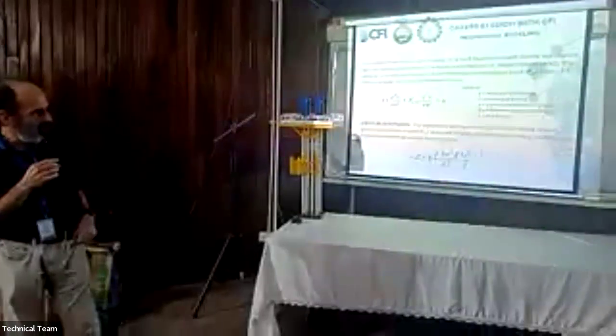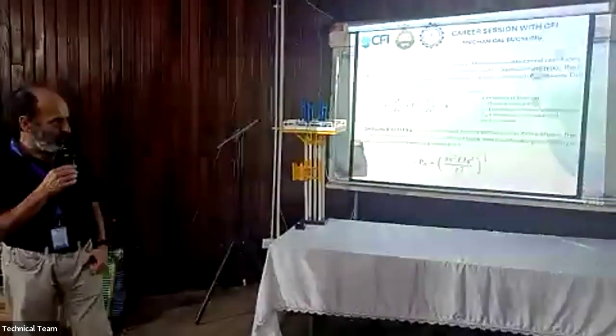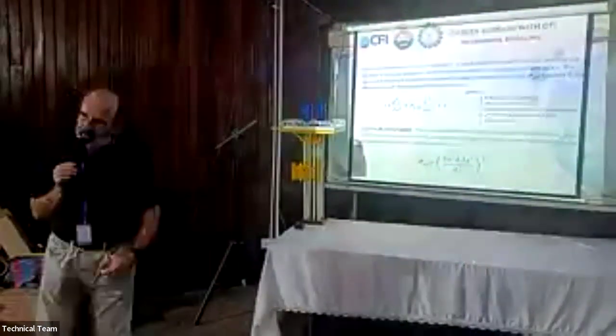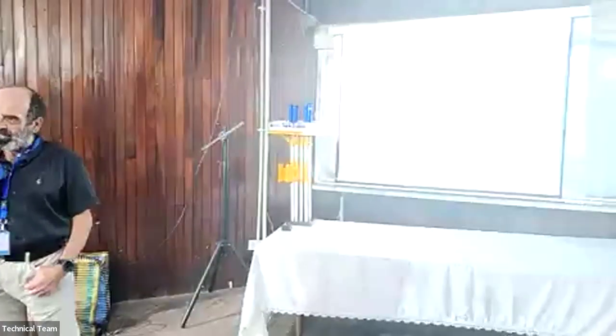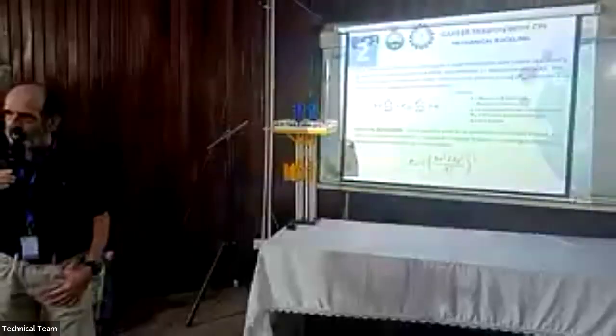And then the one below is the critical pressure, which is also called Euler's equation, to calculate the critical pressure for a pipe of a certain length and a certain moment of inertia. E is always the same on steel, but I would change depending on the diameter of the pipe. So for that, you can calculate a critical pressure. And that to the 1/3 means the same as the third root, not the square root, but the third root of that equation. So like I said, don't worry about that.